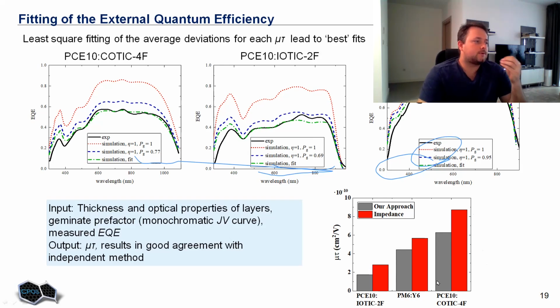So it means that by employing very standard techniques, measuring JV curves and EQEs, and combining them with readily available, free access software, like a Python script for transfer matrix simulation and fitting of simulated and experimentally measured EQEs, we can get valuable quantitative information about extraction and recombination processes in organic solar cells under short circuit conditions.